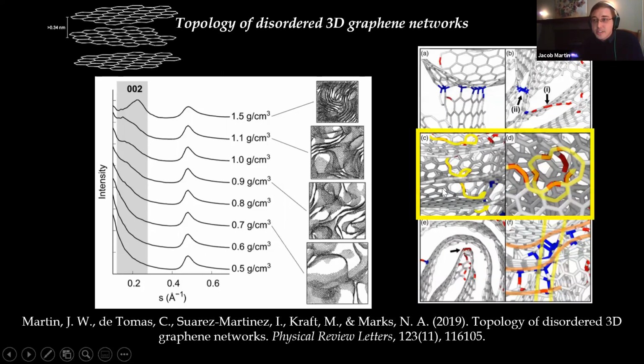I recommend reading the paper if you're interested in more, but the critical one is this screw dislocation. So you see that the layers are actually continuously connected through a screw dislocation, which is the sheets breaking and then winding up in a spiral staircase sort of arrangement. Now, what's really nice about this is that Rosalind Franklin spent a lot of her time looking at helical geometries, and it's quite nice to see that a potential solution to the problem that she first posed on the nanostructure of disordered carbon can also lie in the famed helix geometry.